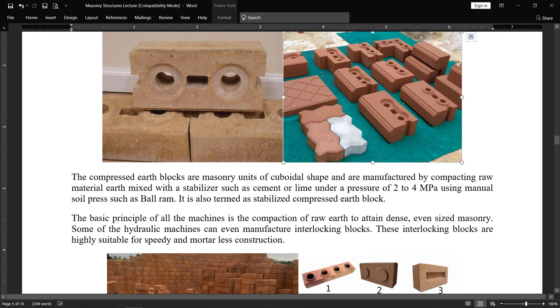The compressed earth blocks are masonry units of cuboidal shape and are manufactured by compacting raw material earth mixed with stabilizers such as cement or lime under a pressure of 2 to 4 megapascal using a manual soil press such as ball ram. It is also termed as stabilized compressed earth block. I have already discussed the compressed earth block. We mix the clay with cement to stabilize its property,